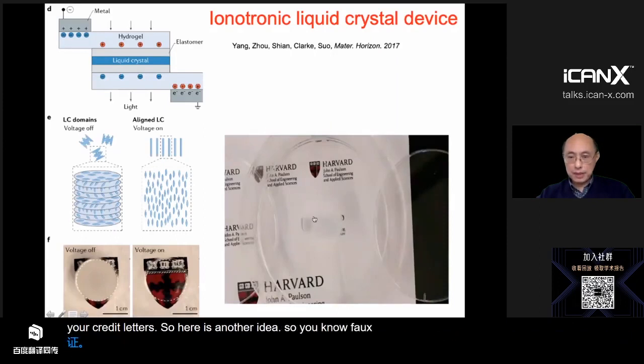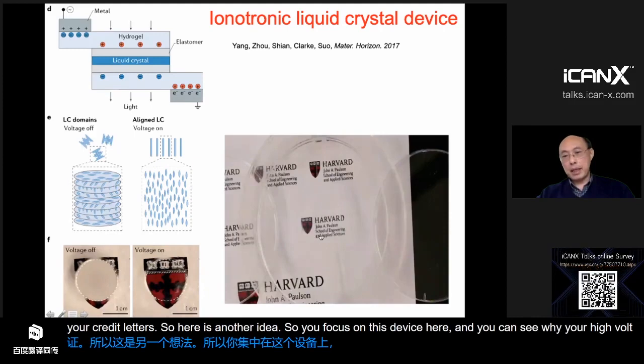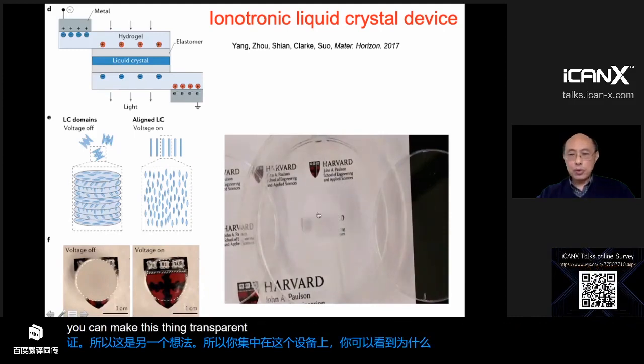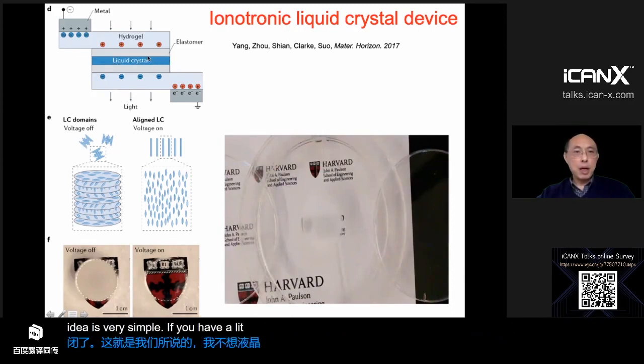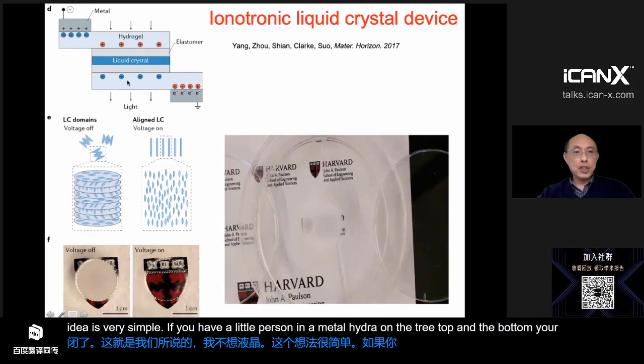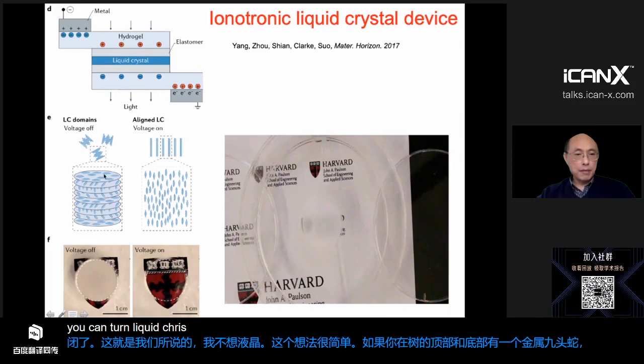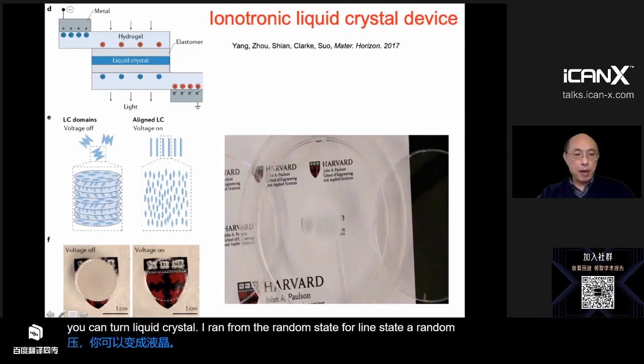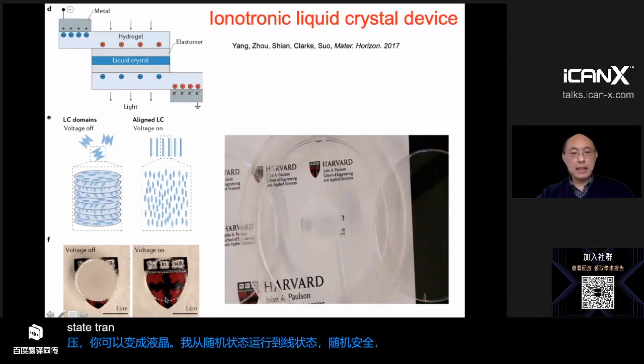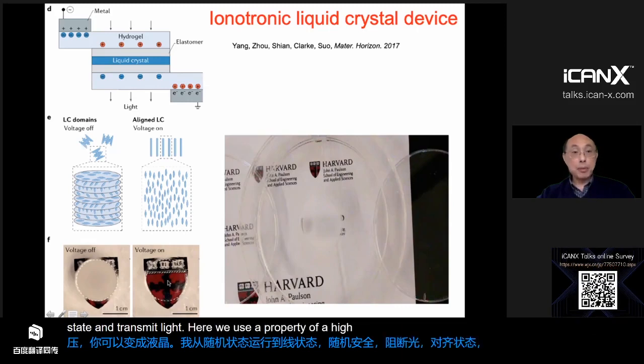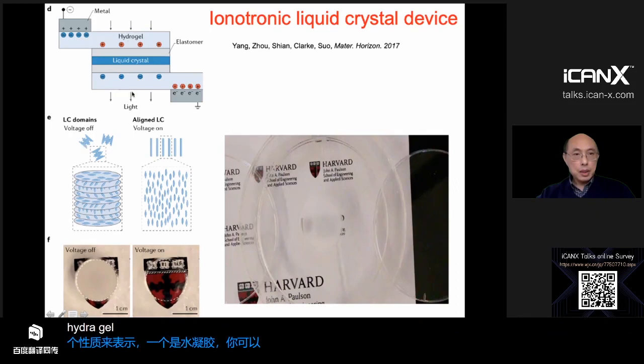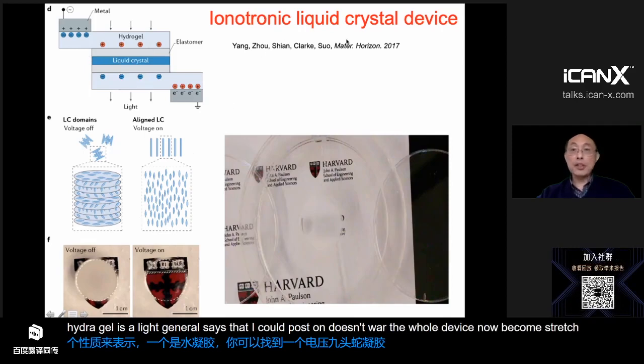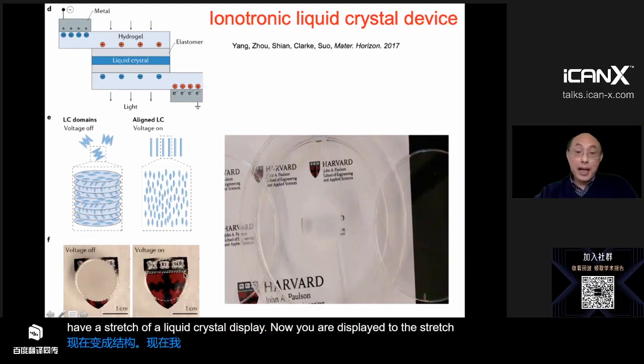So you focus on this device here, and you can see when you apply voltage, you can make this thing transparent and also shut off. This is what we call ionotronic liquid crystal. The idea is very simple. If you have a liquid crystal in the middle, hydrogel on the top and the bottom, you apply voltage, you can turn liquid crystal from the random state to aligned state. In random state, it blocks the light, and in aligned state, it transmits light. Here we use two properties of a hydrogel. One, hydrogel can apply a voltage. Two, the hydrogel is transparent, so the light can go through the liquid crystal. Furthermore, the whole device now becomes stretchable. Now we have a stretchable liquid crystal display. Now your display can be stretchable, highly stretchable display.